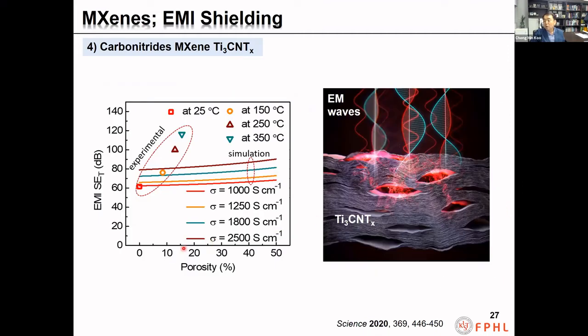That anomalously improved the shielding, the absorption shielding SEA, and the total shielding effectiveness, partially attributed to the improved porosity and conductivity. However, these factors alone do not fully explain the observed increase within the frame of existing shielding theories. It is a much larger improvement than our expectation based on the theoretical calculations. At this stage, we suggested that the anomalously improved absorption may be caused by the metastructure effect that can improve the effective permeability and permittivity, and finally the absorption property.